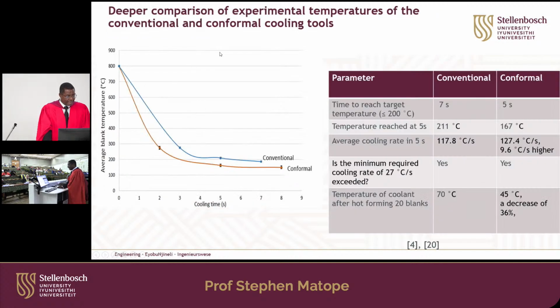See. So with that, we then also did some comparison, taking a closer look here. For our conventional, the straight one, here we go. Then for our conformal, here we go. Comparing this, the time to reach the target temperature of 200 degrees or less: for conventional, we took 7 seconds, but for our conformal, which we came up with, we took 5. Note that at 5 seconds, the cooling is not just coming to 200, it's actually way down, so performing quite a bit better. We're getting 167 degrees Celsius there. But for conventional, at 5 seconds, we're still up.